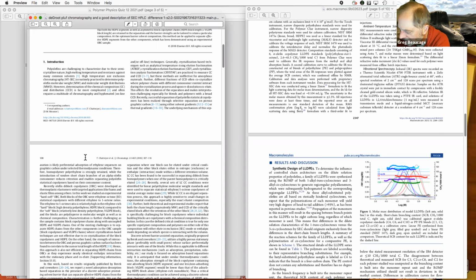But all the moments, since these are monodispersed fractions, every time it comes through, the weight average is the same as the number average, is the same as the viscosity average. To get viscosity average from viscosity, get weight average from light scattering. I think those are the only things they do, right? Light scattering and viscosity, right? But the molecular weights all agree, like they're all going to be exactly the same number. It doesn't matter which way you get it, right? But they can get radii of gyration here. Then from the viscosity, they can get the hydrodynamic radius from the intrinsic viscosity, right? That's going to be the hydrodynamic radius cubed divided by molecular weight, right? So you can get hydrodynamic radius and radius of gyration out of this setup.